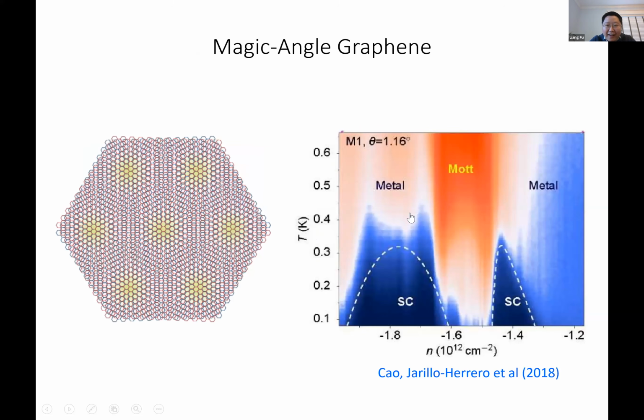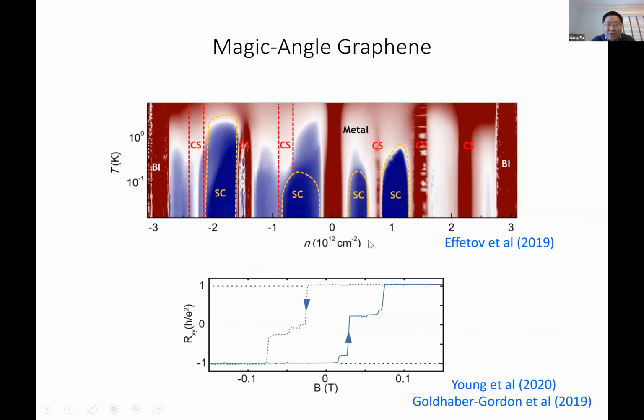Starting from about 2 years ago, there was a new breakthrough coming from my colleague Pablo Jarillo-Herrero's group at MIT. These are magic angle graphene, 2 sheets of graphene with a specific twist angle around 1.1 degrees. Here you see that a wide variety of unexpected phases appear, including Moiré-like insulating states, as well as superconducting domes, which have certain similarities to this cuprate phase diagram. This field has been evolving extremely rapidly.